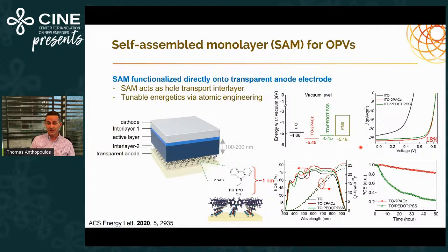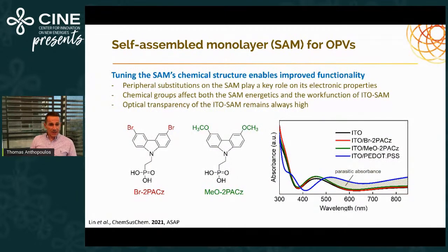So these self-assembled monolayers appear to impact not just the energetics of the interface in the case of organic solar cells, but also the morphology of the bulk heterojunction. This is how big the impact is on the optical properties of the electrode. Here we're comparing these two self-assembled monolayers functionalized directly on ITO against the PEDOT:PSS ITO electrode, and we can see that all this parasitic absorption can be suppressed by simply switching to a self-assembled monolayer.